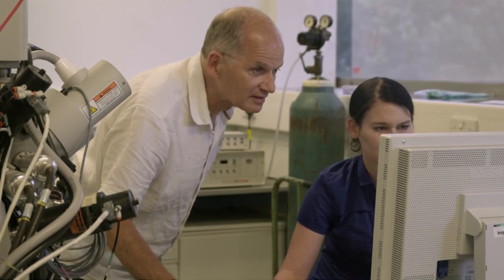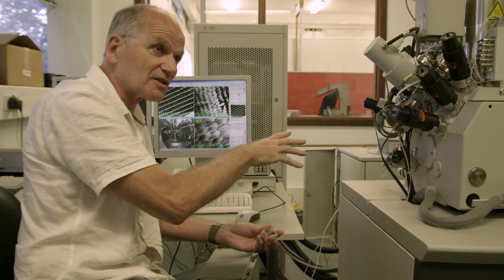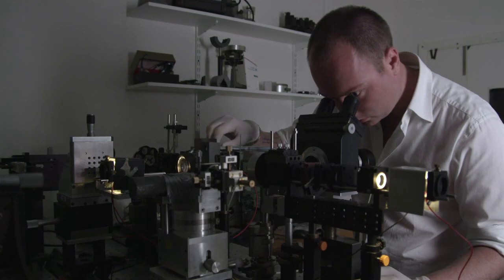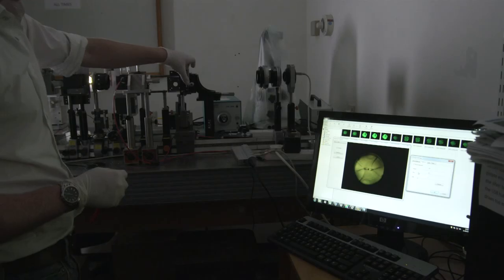There was a fascinating paper by some South African scientists looking at a particular moth with a gold metallic spot on its wing. It turns out it uses a zigzag grating — basically a grating that you zigzag. Zigzag gratings haven't really been studied before, and they're fascinating — they have weird polarization and diffraction properties. We then make zigzag gratings, metalize them, and they have very interesting optical diffractive properties. If flat silver is placed into the scatterometer, all we see is reflected green light. But if we pattern the silver surface with a grating, we see missing portions of light.